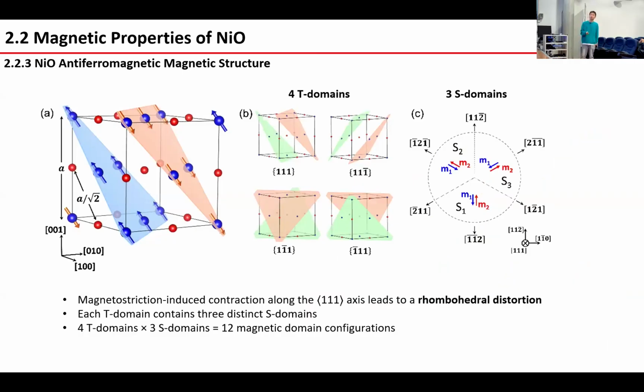So before studying the spin current transport, let me introduce some of the magnetic properties of the nickelate. The antiferromagnetic interaction comes from a superexchange interaction mediated by the oxygen, forming the nickel-oxygen-nickel bonding along the 100 direction, for example, and the spins in the nickel form an antiferromagnetic alignment along the 101 orientation. And there's also a ferromagnetic alignment along the (111) plane.